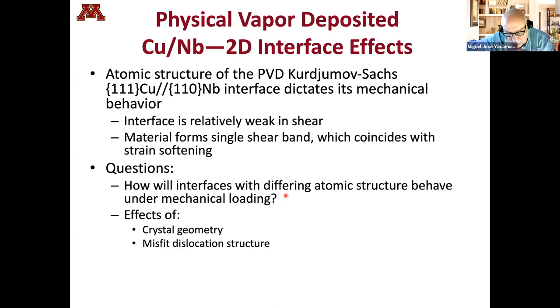One question. What do you use for doing the strain inside the microscope? Was it an AFM tip, or what was the device? So we use what's called a pico indenter. It's made by Bruker. There are other brands out there as well. It's basically an in-situ straining stage in the scanning electron microscope. Okay. So it's kind of like what our colleagues do with AFM, but at much higher loads. Mm-hmm. That's the main difference.